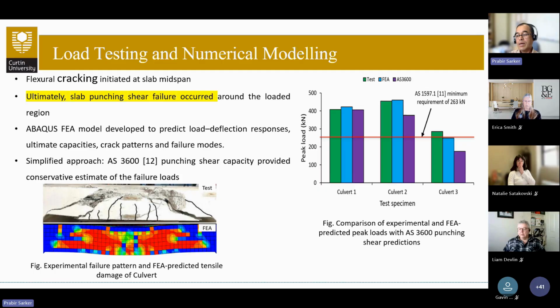We also looked at the comparison of the test load with the estimated punching shear capacity calculated by the Australian standard for the slab. This diagram on the right hand side shows the comparison between the test load at failure, the finite element analysis prediction by Abaqus, and also the AS3600 punching shear capacity prediction. We can see that the load capacity at failure could be predicted with good accuracy, close to the test failure load, and the punching shear capacity from the Australian standard is generally more conservative than the finite element analysis.